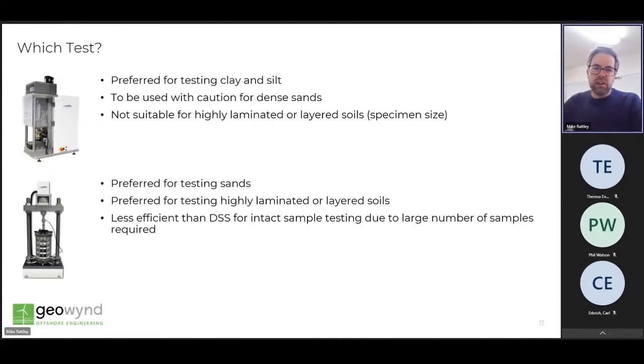So despite some limitations, both the DSS and triaxial tests offer convenient and relatable measurements of cyclic soil response that we can use for design. DSS tests are typically preferred for clay and silt soils, but should be used with caution for testing dense sand due to the non-uniformities that can arise, or other highly dilatant soils and weak rocks. The test itself is unlikely to be suitable for testing laminated soils due to the limited sample size. Triaxial tests are probably preferred for testing of sands and certainly for laminated or variable soils. However, the triaxial tests are less efficient than the DSS test for testing intact samples, as discussed earlier, due to the lower number of test specimens that can be obtained from a small number of core samples.